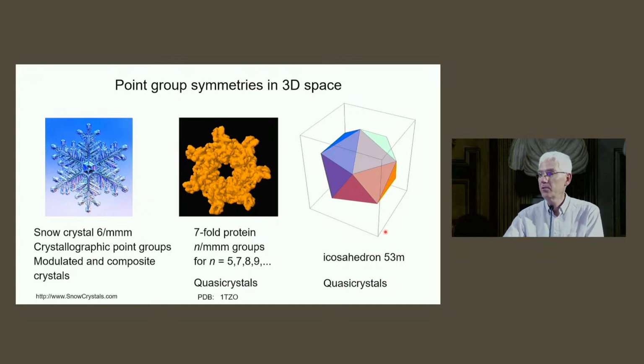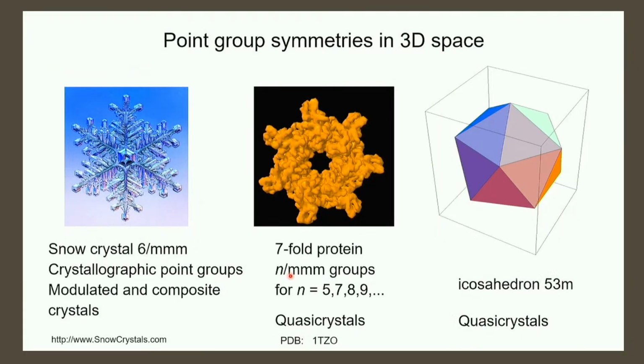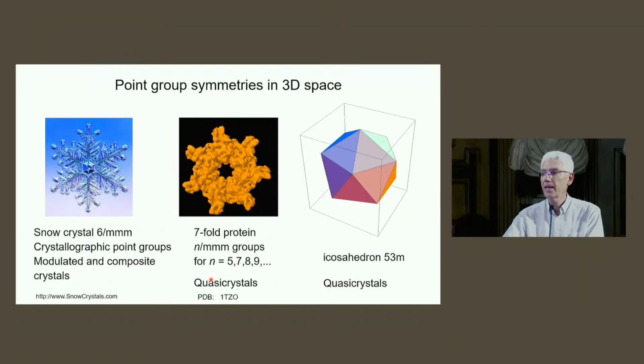And then we have special groups. On the left side, a special group is, for example, the cubic symmetry group, which combines 4-fold and 3-fold axes, whereas n/mmm has only 1 n-fold axis and quite a few 2-fold axes, but no combinations. And the other non-crystallographic combination is the icosahedral group, which contains 5-fold and 3-fold axes, and which is found, as said by Giovanni, for quasi-crystals. Also the other n/mmm based point groups can be the symmetry of quasi-crystals, and several have been found. But there are no more point groups to consider, and for the superspace groups it really is only the crystallographic point groups that we need. And otherwise we are with quasi-crystals.